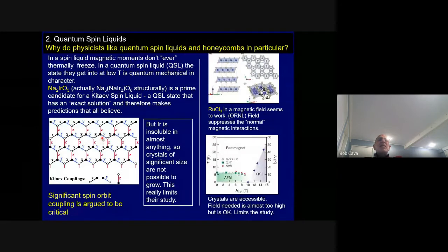And a honeycomb lattice, you can see right here, every uncolored ball is surrounded by 3 balls of the opposite color. And so you can actually write down a model for how magnetic interactions could happen on such a lattice to yield a state at low temperature where you just have entanglement of spin-1/2 particles on this lattice, if you can actually find a material that does that. And although sodium 2 IrO3 was the first one that was found, it's not possible to grow big crystals of this material because iridium is not soluble in anything.